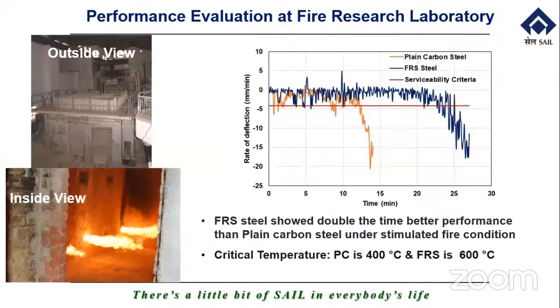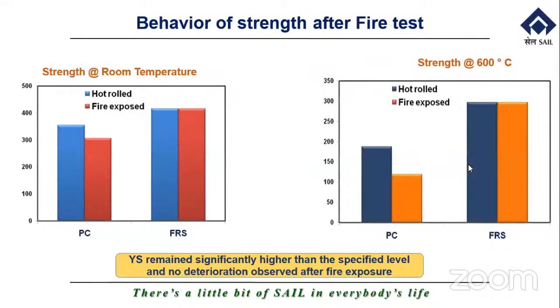The critical temperature for plain carbon steel is 400 degrees centigrade only, and for FRS it is escalated up to 600 degrees centigrade. Now, the yield strength remained significantly higher than the specified level, and no deterioration is observed when it is exposed to fire, when it is fire resistant steel, which we can see here in the graphs.